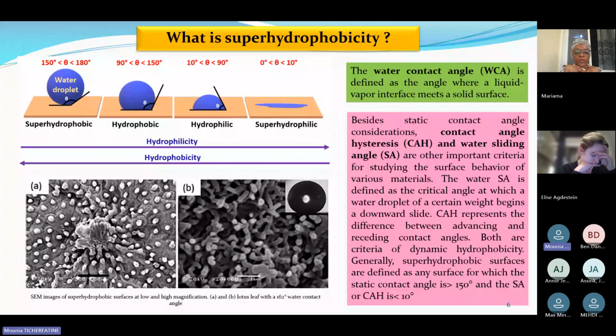Superhydrophobicity was initially discovered in nature, as we can see here from the SEM image in the bottom left. We can see superhydrophobic surfaces at low and high magnification of a lotus leaf. Here we have a WCA of 162 degrees, which is a superhydrophobic surface.